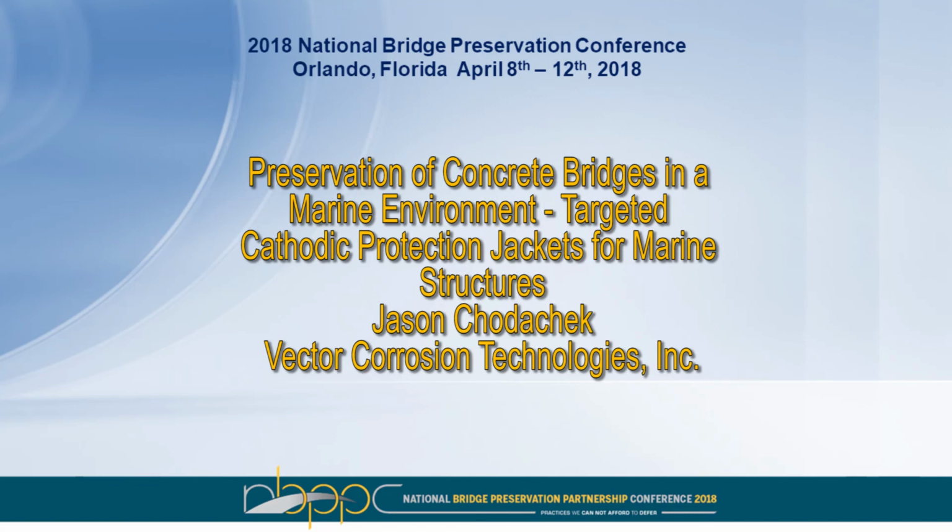Right. Now, if you're wanting to extend a jacket up, if you do have damage on a structure that's extending up a lot farther out of that wet zone, tidal or splash zone, your zinc is going to lose its activation. It's not going to remain active, and so you're going to have to look at more of an alkali activated system, one that's going to keep the zinc in an active state. So it is possible to use two different systems on the same structure or the same pile. You could use a wicking or a standard tidal jacket below, and then switch to an alkali activated system above. Thank you.